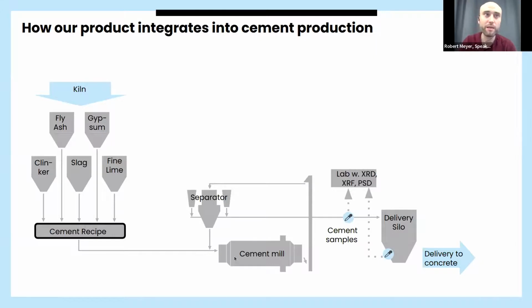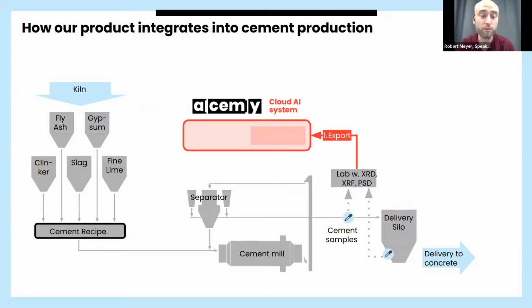But it doesn't end here. Right after the separator, before the cement enters the silo, they take regular samples. These samples are automatically analyzed with X-ray diffraction, X-ray fluorescence, and a particle size analyzer. This gives us the full picture of the material: the mineralogy, the chemical composition, and the distribution of particle sizes. This full picture is then exported into our cloud system, where we run a machine learning algorithm to predict the strength it would develop if I formed a cube out of it, let it sit for 28 days and crushed it. So really, we predict the 28-day strength of the material.